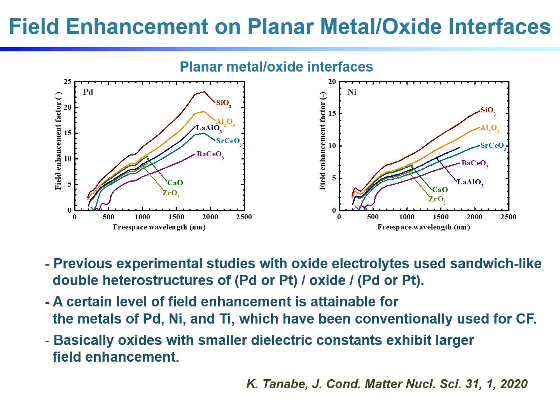Not only metal surfaces, but also metal-oxide interfaces contain surface plasmons. For planar interfaces of the common combinations of metals and oxides experimentally investigated in the community, we calculated the field enhancement factors. Then we found that a certain degree of field enhancement is attainable for palladium, nickel, and titanium. And basically, oxides with smaller dielectric constants exhibit larger field enhancement.